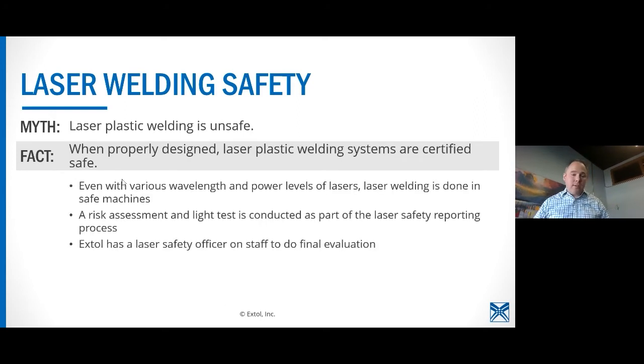So even with various wavelengths, we typically use 980 nanometers. You can have low-end 900 nanometer, even lower than that, up to 2000 nanometers or 2 micron. Laser welding is done in safe machines, and we ensure it by a risk assessment in the design process if it's a custom configured solution. And then we do an end-of-line light test as part of the safety reporting process that we need to do for the FDA. And then we have a certified laser safety officer on staff to do that evaluation. So that's crucial. If you're thinking, well, I want to see if I can do this with another source, that is a very key item to make sure that you are safe in your laser welding system.